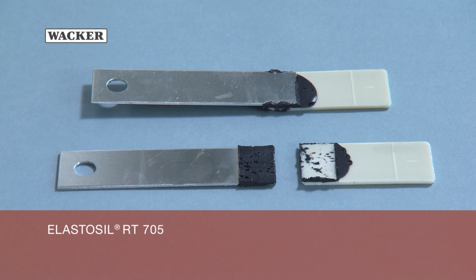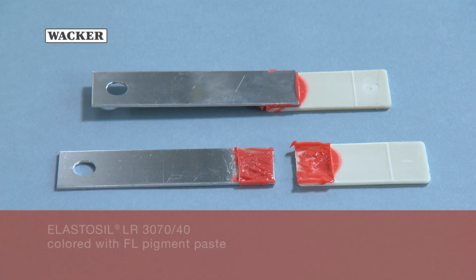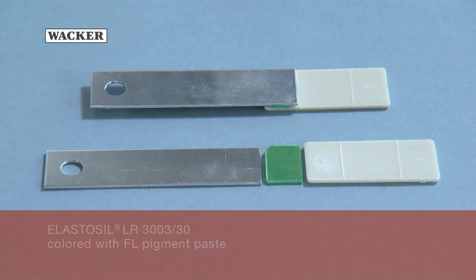By comparison, RT 705 undergoes nearly complete adhesive failure on PBT, which is generally undesirable. On both substrates, ELASTOSIL 3070/40 exhibits cohesive failure almost exclusively. Silicone grades that are not self-adhesive, such as ELASTOSIL LR 3003/30, do not usually bond to any material.